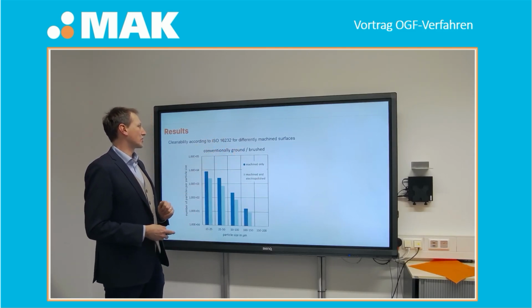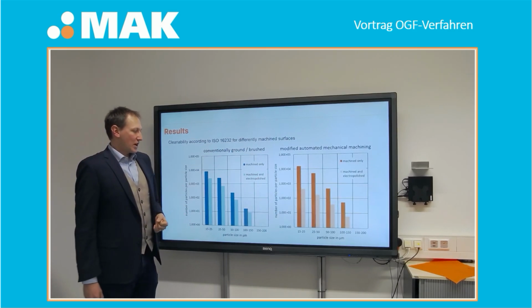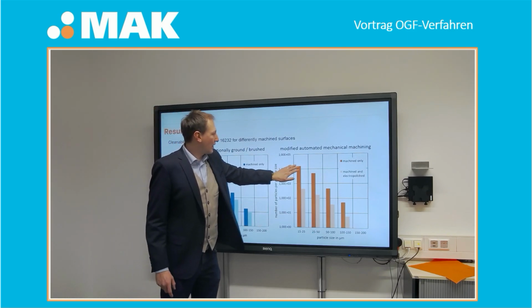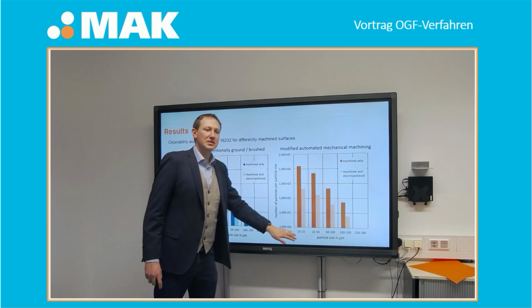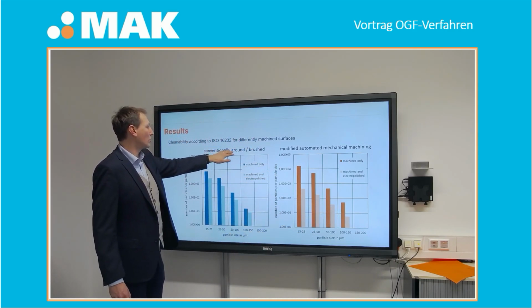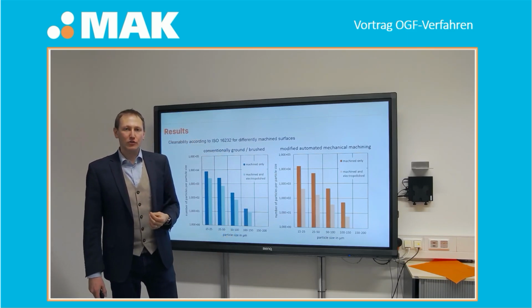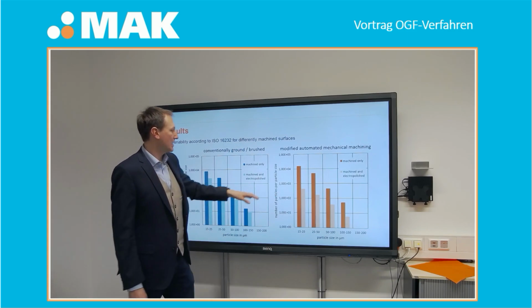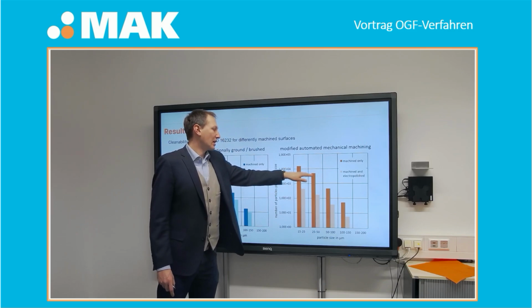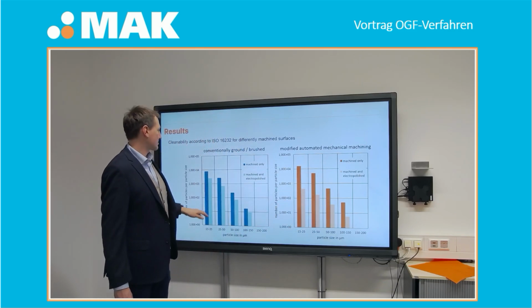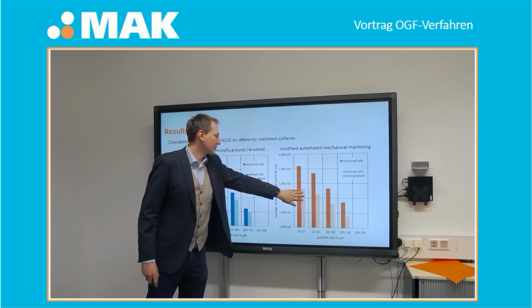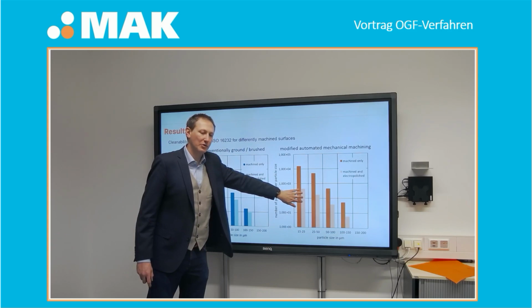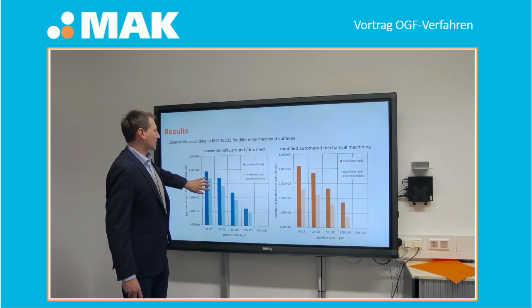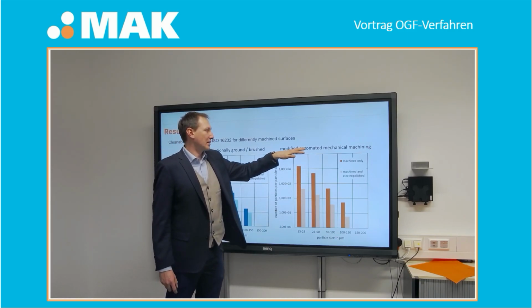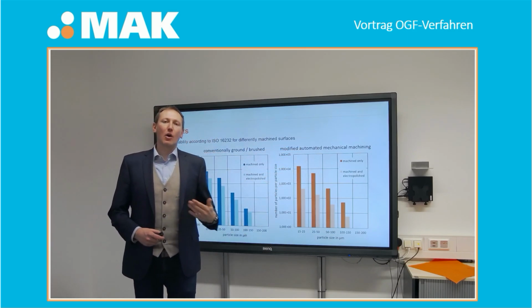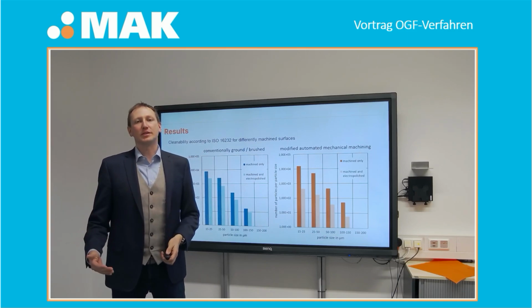This is for the conventional grinding. If you do the OGF process, you can see that only after OGF the number of particles left on the surface is increased compared to only grinding. But if you do electropolishing on this surface afterwards, you can see a very strong reduction of the particles left on the surface. Especially if you compare the number of particles left on the surface after OGF and electropolishing to the particles after conventional grinding and electropolishing, you can see that there is an increase of cleanability by the OGF process in combination with electropolishing.